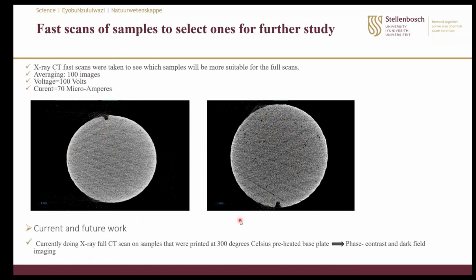So I'm currently doing a full CT scan on those samples printed at this base plate temperature. From there, I'll be moving to do the phase contrast and dark field imaging at VETS, and then compare the results and conclude whether I can use the system as a non-destructive testing method.